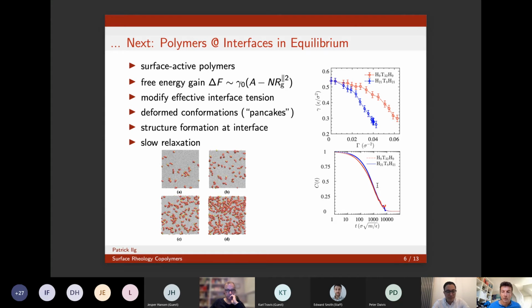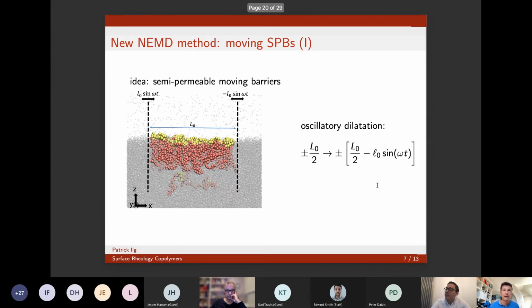Okay, so now finally coming to the rheology. How do we do that? So again, the problem is you want to only deform the interface and not the bulk, and you want to compress it. And so our idea was to use semi-permeable moving barriers. So on the left, you have a snapshot of the system. In gray are the water molecules. So we have a liquid phase down here, a vapor phase up here, and we have our pluronic molecules at the interface, the hydrophilic ones pointing inside and the hydrophobic ones on the surface. So that's how it should be.